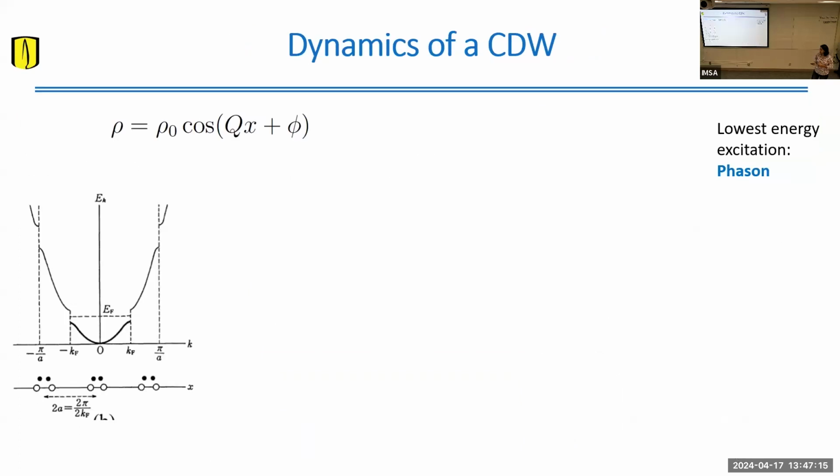So these charge density waves have many details that could complicate this landscape that we are trying to understand. A charge density wave, you can characterize it by a periodic arrangement of your charge density with a characteristic wave vector that is the one that nests your Fermi surface. This picture that I'm telling you here comes from Peierls, which considers only the electronic point of view.